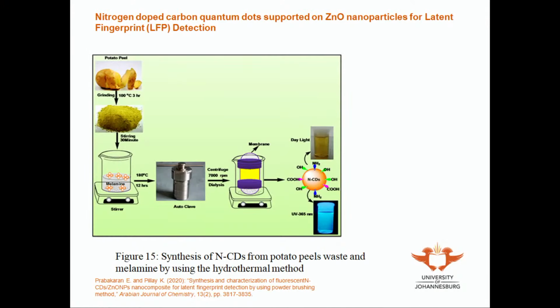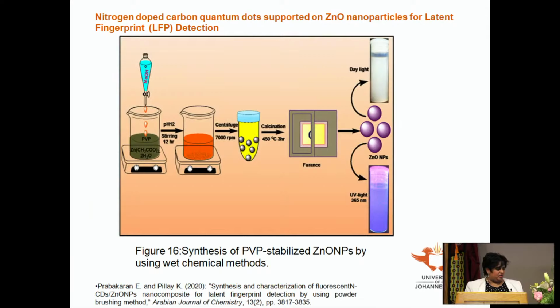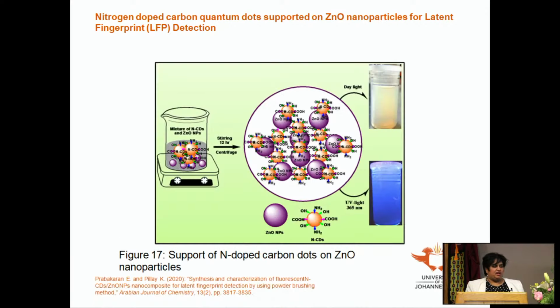Okay, so I've said enough about the water treatment applications. Now coming to the pure forensic applications that we've dealt with. What we did in one of our studies is we prepared nitrogen-doped carbon dots from potato peel waste. And then we also prepared zinc oxide nanoparticles using a simple sol gel method. And we prepared a composite material of the two by simple adsorption technique and used that for latent fingerprint detection.